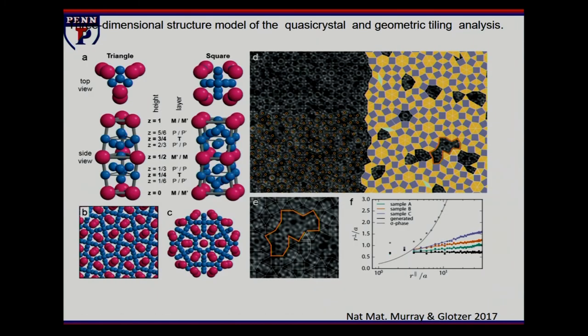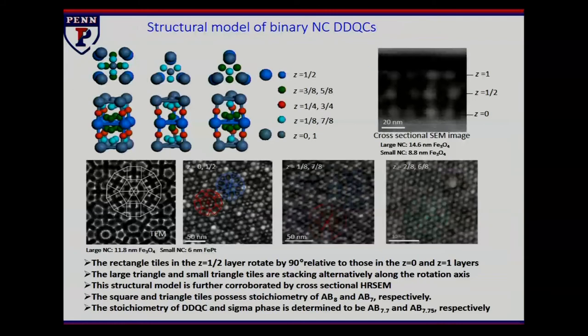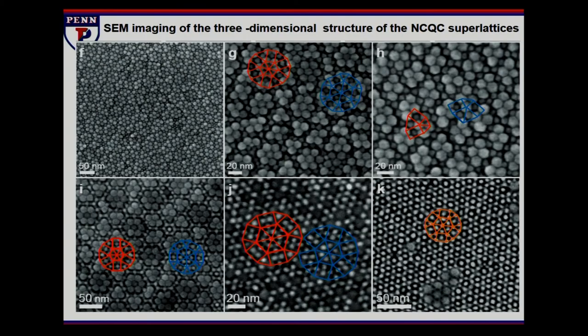And they bring up a very intriguing possibility, and that is that this is a material that has fundamentally two different regimes of physics that it has to satisfy on different length scales. So at nanometer length scales and tens of nanometers, it's crystalline, because the particles are crystalline and they have their extended physical properties. But from tens to hundreds of nanometers, they're aperiodic.